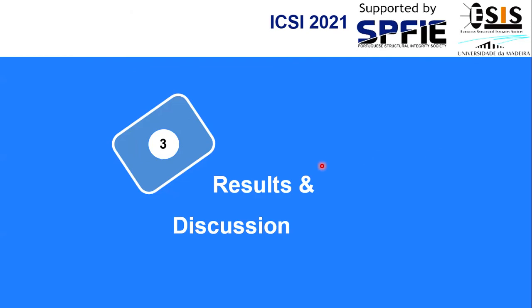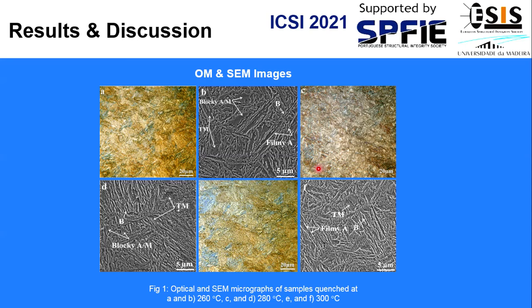Part 3, results and discussion. Here in this slide you can see optical and scanning electron microscope micrographs of samples quenched at different temperatures. According to these micrographs, we found that with decreasing quenching temperature, the steel quenched at 260 degrees Celsius had a high volume fraction of tempered martensite like this and this, and a high volume fraction of blocky austenite or martensite like this and these phases.